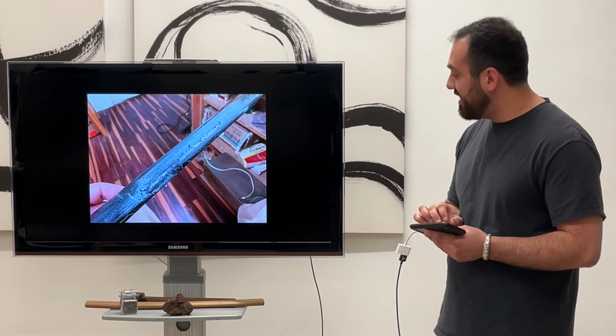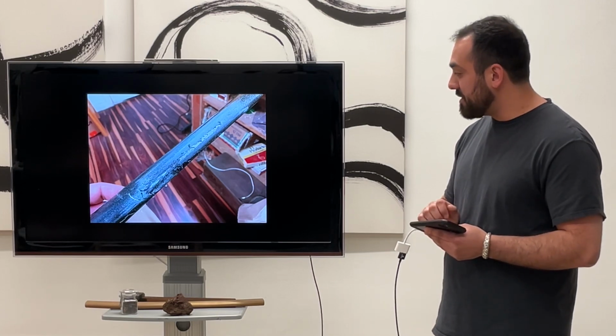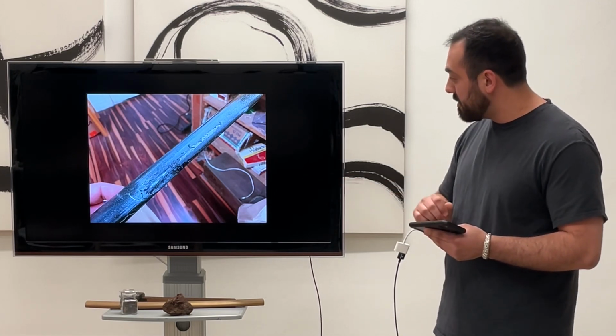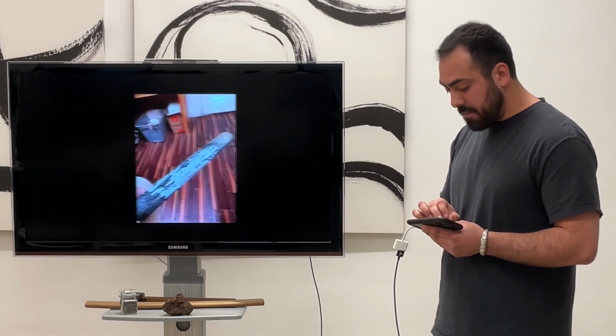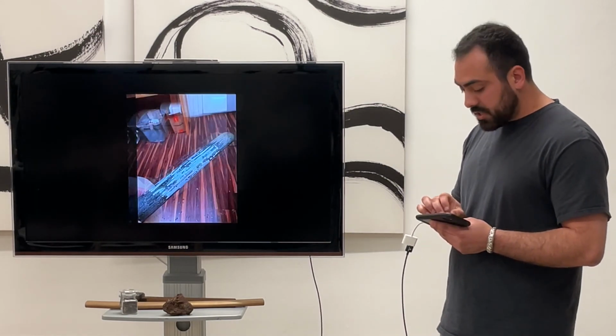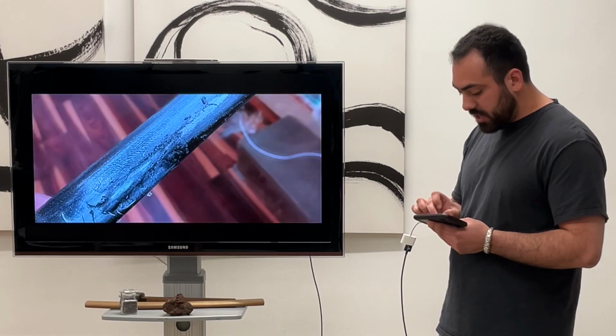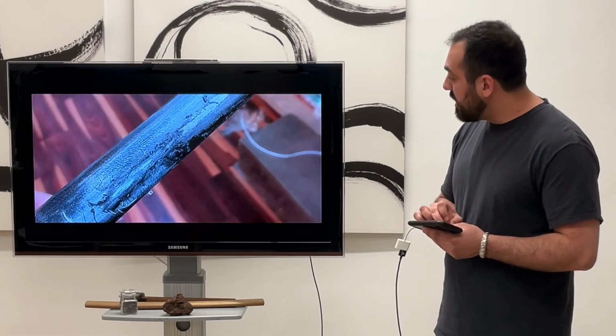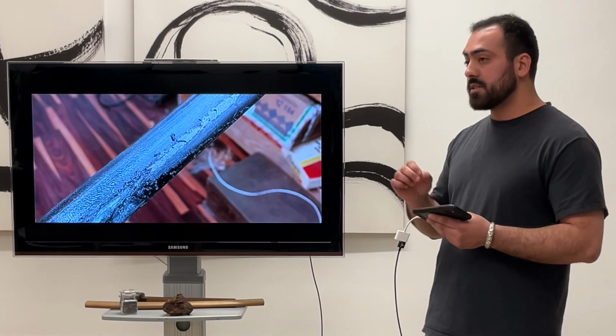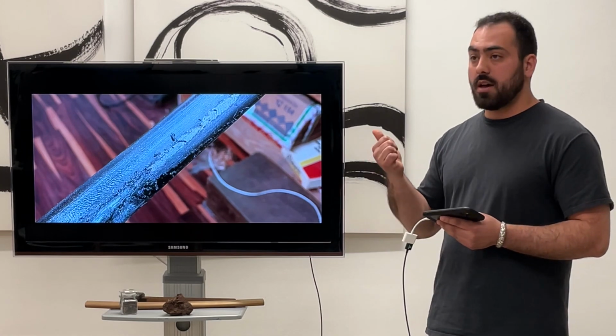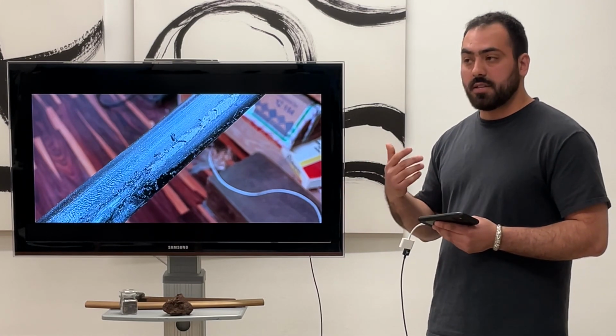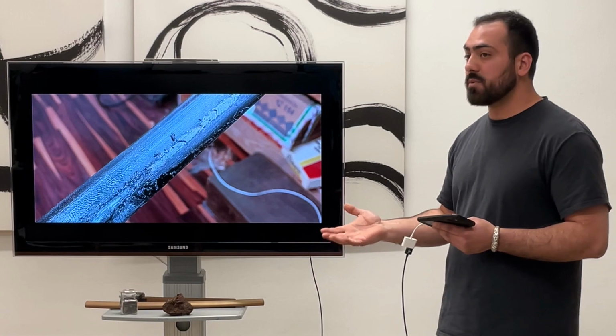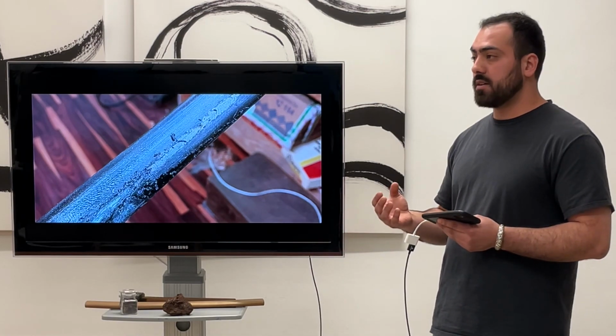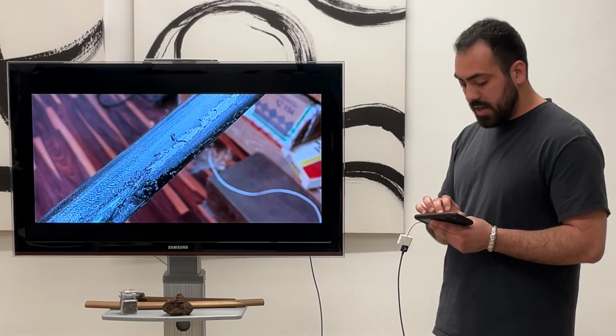I took the kogatana that's in there and just used it to scrape all the bad paint off. And you can actually see here the gummy looking stuff that's underneath the surface was because the room wasn't heated enough. I didn't give it enough time. It's basically the issue with doing any of this sort of work in the winter. You have to have an environment that's suitable for it.